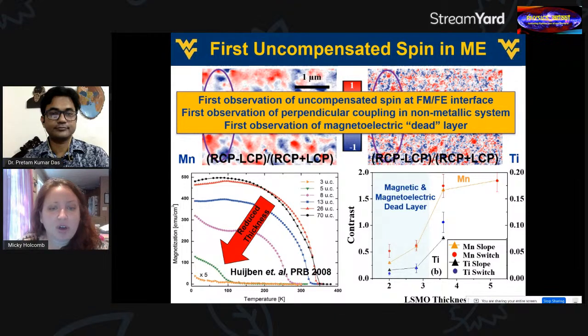And so people have often called this having a magnetic dead layer. So basically suggesting that there's some region of the film that is magnetically dead. And if you make the film too thin, then almost all of your film is dead. Now, I think that that is not an appropriate term for it. Our evidence seems to show that it's a lot more complicated than that. Nothing is actually dead, but you do have some interesting competition going on in the system. And when you make the film thinner, it certainly leads to some more interesting dynamics in the system. So that's what we're going to talk about.